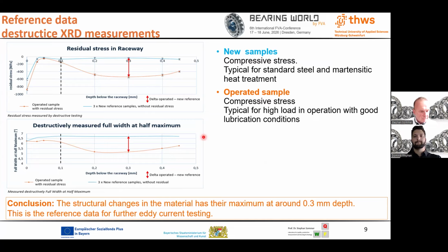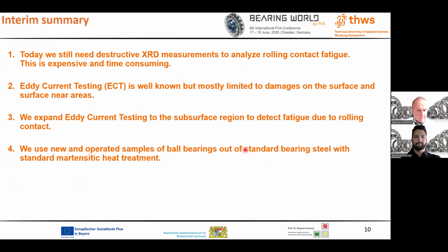So the conclusion is, the structural changes in the material have the maximum at around 0.3 millimeter in depth. This is here. And this is the reference data for further eddy current testing.